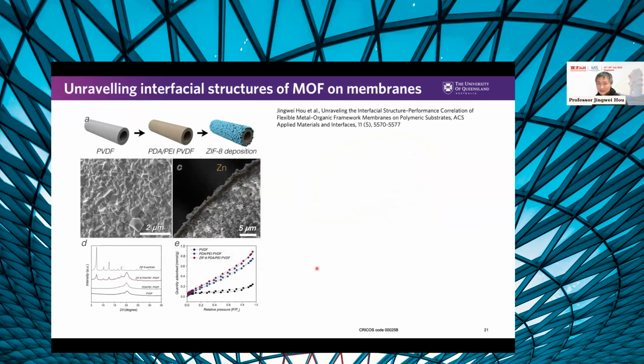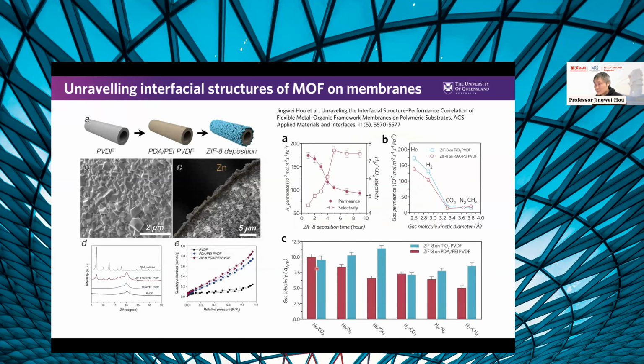We started with exactly the same type of substrate. We synthesized it, we coated the polymer with polydopamine, then we tried to grow it. We did exactly the same. The membrane looks very similar, but when we tested the membrane, we found, okay, it's quite different. I mean, it's not that different. If you look at helium CO2 separation efficiency, they're quite comparable.